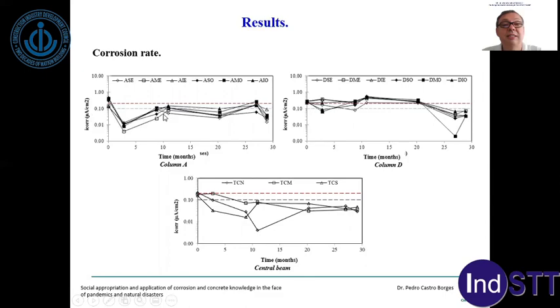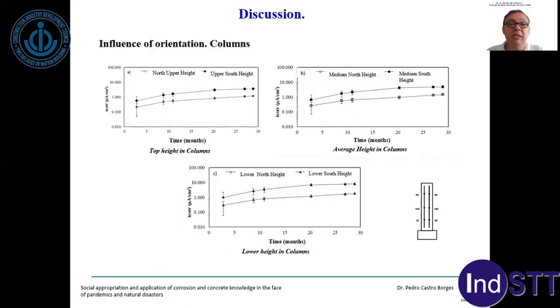All the tendencies of the cumulative corrosion rate show us that the north upper height is always below the south upper height. The same happens at the top, at the average, and at the lower heights. And that is very interesting. We have on the south the marsh, and the marsh is producing a constant humidity, and for this reason, the time of wetness is higher than on the north side where we have the sea. Where we have the sea, we have tides, we have north winds, but we have very specific cycles of wetting and drying, and that is the reason why the time of wetness is less than on the south face.